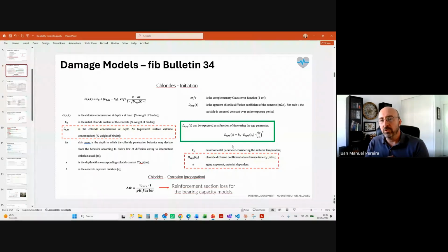So the advantage of what we do is that all of these things that are probabilistic, like the alpha is probabilistic here, this K is probabilistic, we actually measure. So we replace all these probabilistic things with actual measurements. So that reduces the risk, and increases the trustworthiness of the prediction much more, because you are removing variables. We are replacing these probability distributions with an actual thing.